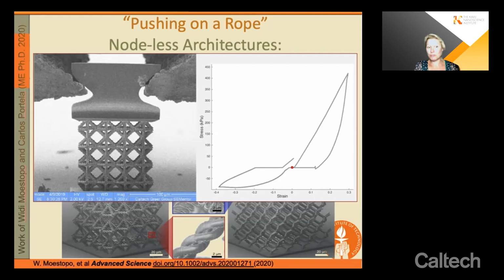And we were able to show that at the same stiffness that you would normally have in tiles, for example, for the space shuttle, you could tune the thermal conductivity and the thermal properties in general of these materials such that they're decoupled from the modulus. So you could make something very, very lightweight and at the same time extremely thermally conductive or extremely thermally insulating. That has everything to do with the phonon mean free path in the specific material.